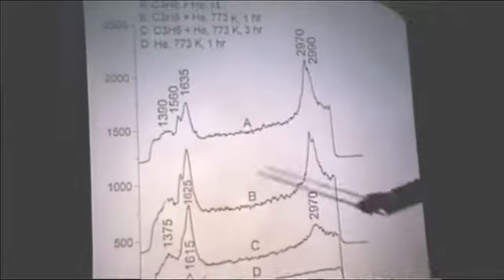In fact, Frank and Jeff already knew that this was what would happen because they'd done the carbon-13 NMR on exactly the same condition, and they wanted to find out if we could get the right answer, if you will. So we did. We got the right answer, and we see this polyolefin on the surface. The one band that we don't know what it is in the spectrum is this band at 1560, and it isn't always there, so at least for this discussion, I'm going to ignore it.